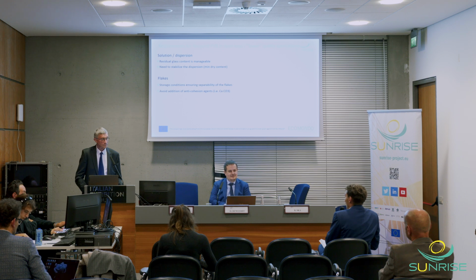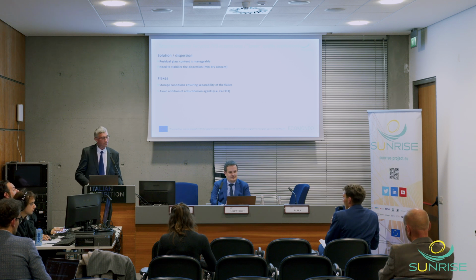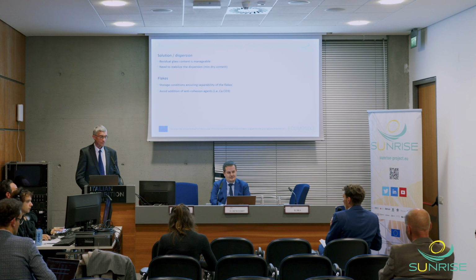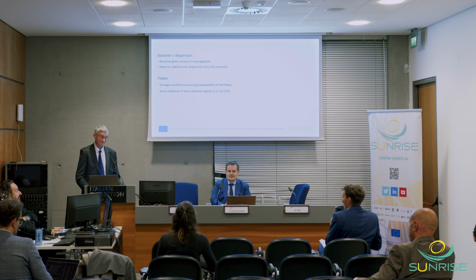But in respect to the recycling of PVB, how we feed the material into our new technology, we can process it as flakes. When the flakes have a really low ash content or glass residue, then we can process it. And it's not a problem to use a guillotine to cut it into pieces and then reuse it in our production facilities. But the quality has to be established. Only then we can use it. Minimum quality standards, yeah. Minimum, yeah.